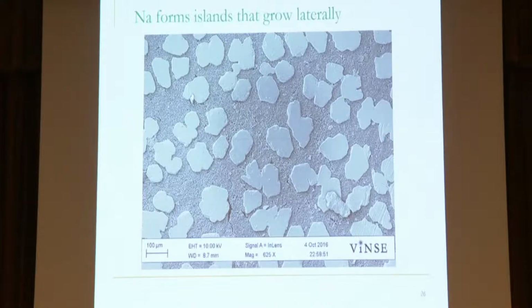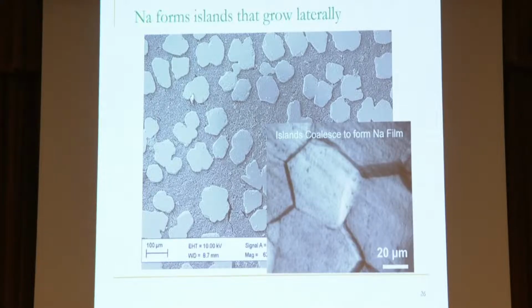We can take this to a microscope which uses electrons instead of light. Because electrons have a much smaller wavelength, we can see much smaller features in this material, and something fascinating happens. We have this crystalline sodium film. So I get asked the question all the time, hey, Professor Pint, lithium forms dendrites. Sodium should too. No. Lithium forms dendrites because it's unstable in liquid electrolytes. This is stable. So it plates as a crystalline layer, right? There's no side reactions that would cause instabilities, things to break down, and as a result, dendrites, which would catastrophically short and destroy the device.